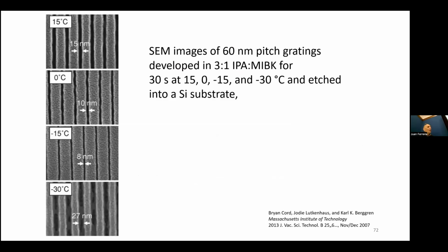Now, a way that we can improve contrast is by doing cold development, at least for positive resist. This is not going to work well for negative resist, but positive resist, where the area of the resist that you expose is the area that gets washed away.